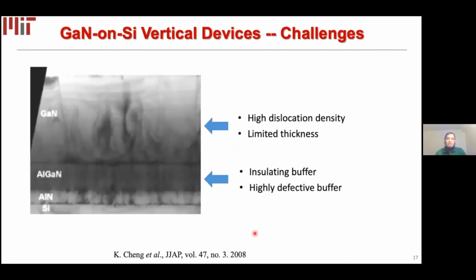For example, here is a cross-section SEM from the literature, showing a typical GaN on silicon wafer where the dislocation density is very high and thickness is limited to avoid cracking. Also, due to the presence of insulating and defective buffer, the transport can be very challenging through this kind of structure.